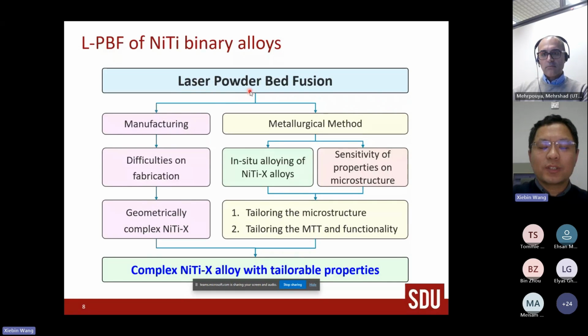And then we want to use laser powder bed fusion as a metallurgical method to do in situ alloying to make nickel titanium ternary alloys, using, for example, nickel titanium powders and niobium powders to make nickel titanium niobium ternary alloys. And also we want to use laser powder bed fusion to tailor its microstructure and transformation behavior, and of course the functional properties.